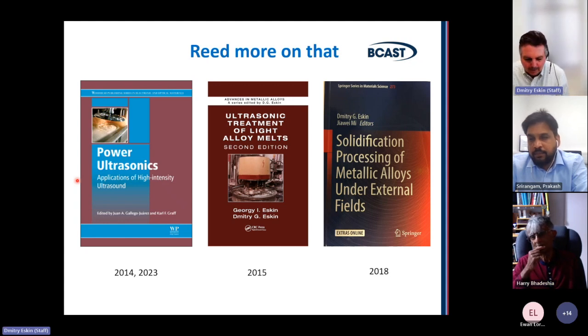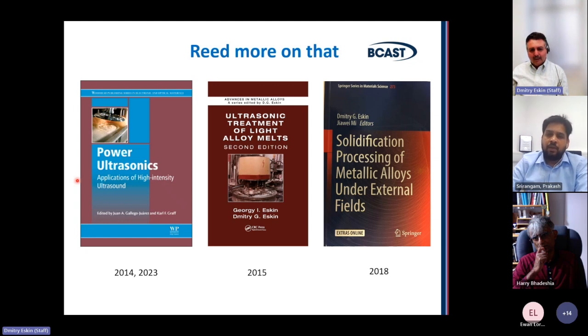Yeah, thank you. It's a very clear question, and I have a clear answer to that. There are two aspects here. One aspect: if we try to use what we use in the liquid aluminium, so direct introduction of ultrasound using the sonotrode inserted into the liquid melt, unfortunately, we don't have materials which can be stable in liquid steel at these temperatures and then transmit the acoustic wave. So there is no way to directly introduce ultrasound in liquid steel, or for that matter, other high temperature materials like titanium or nickel and so on. So that's the straightforward answer.